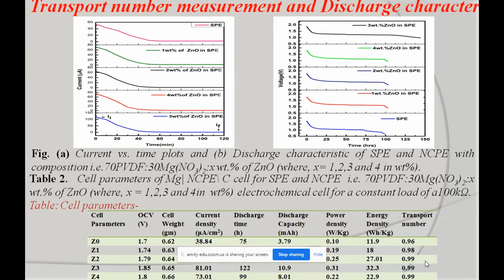The second figure represents the discharge plot, plotted between voltage and time. We discharge our electrolyte by fabricating an electrochemical cell in the configuration of anode, electrolyte, and cathode. We will calculate all cell parameters like current density, discharge time, discharge capacity, power density, and energy density. For our optimum system, we got an OCV value of 1.85 volt and a current density of 81.01 microampere per centimeter square, and all these parameters are listed in our table.